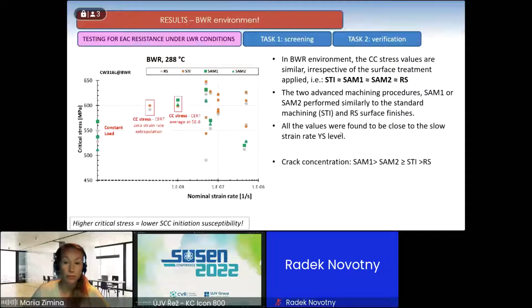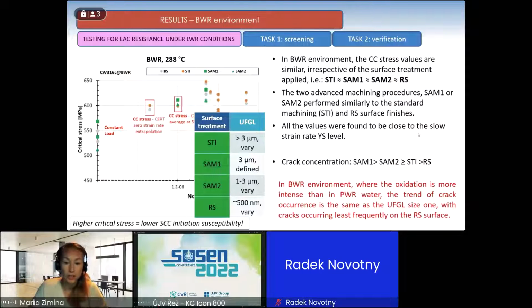Yeah, all values were found to be close to the slow strain rate yield strength level, and the crack concentration, which was calculated using SEM, also followed this rule: the highest crack concentration was observed in SAM1, less in SAM2, less in STI, and then the reference surface, which suspiciously follows the size of the ultrafine grain layer. And we think that in the BWR environment, where the oxidation is more intense than in, for example, PWR water, it can be explained by the oxidizing conditions.